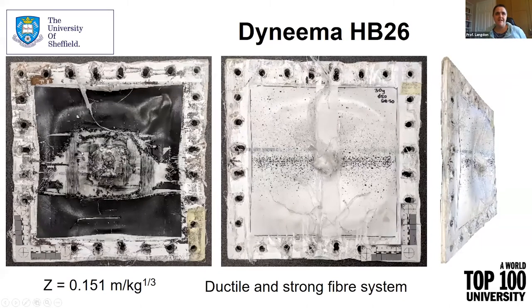And you can see there a nice area of melting in the center, which is probably where the fireball interacted with the Dyneema. On the rear side, you can see that strip that I talked about with the speckle pattern on it. You can also see a sort of bushy area in the center. That's a lot of fiber fracture that's happened there in the central region. There's large permanent bulging and reverse snap-through buckling, which is easiest to see from the diagonally positioned image on the far right of your screen, where you can see much more just how much deformation has happened to that panel. And the small perforated section in the middle.